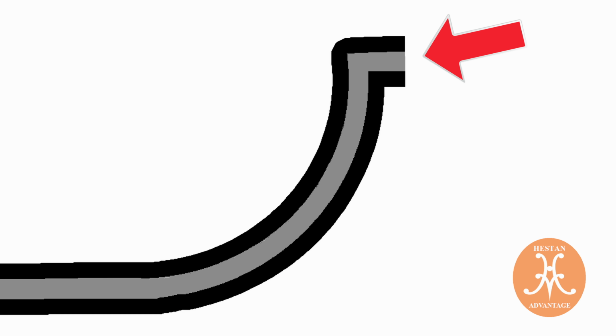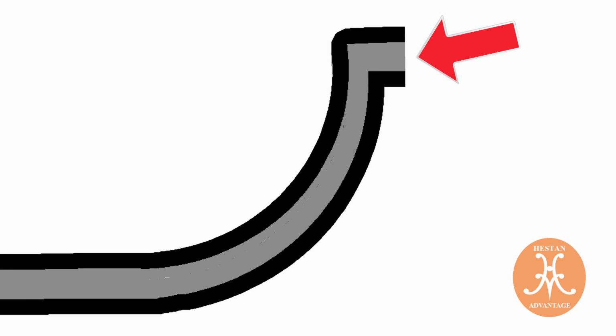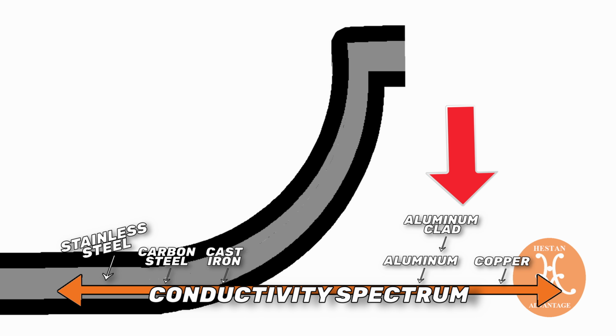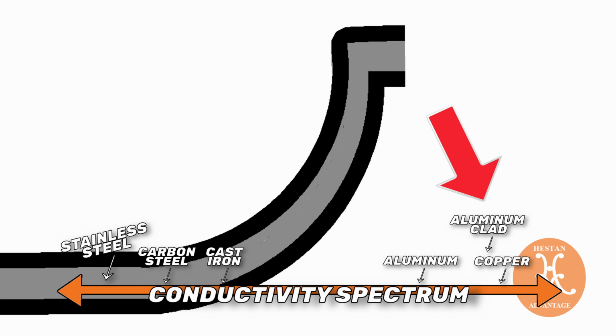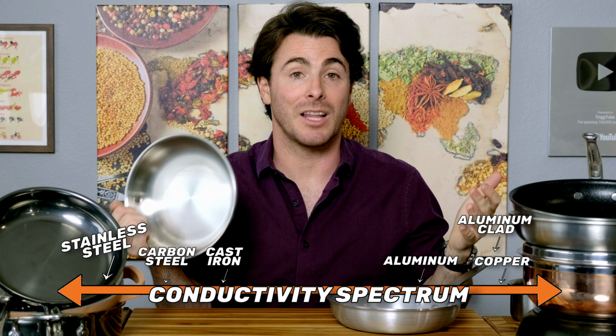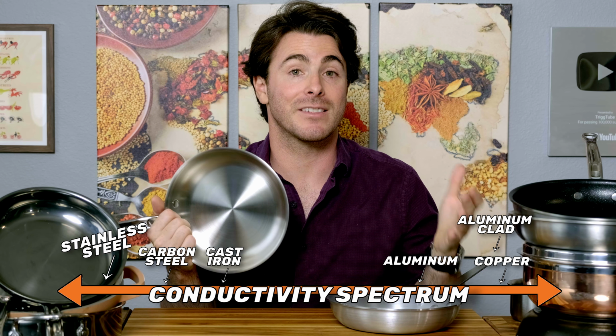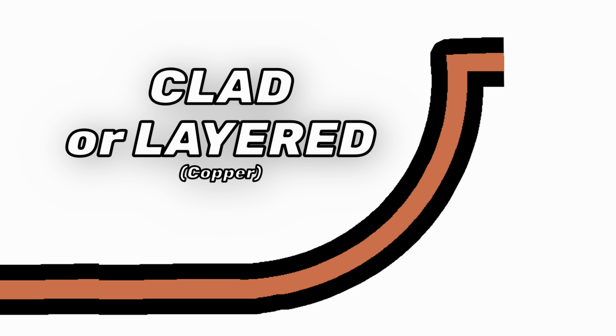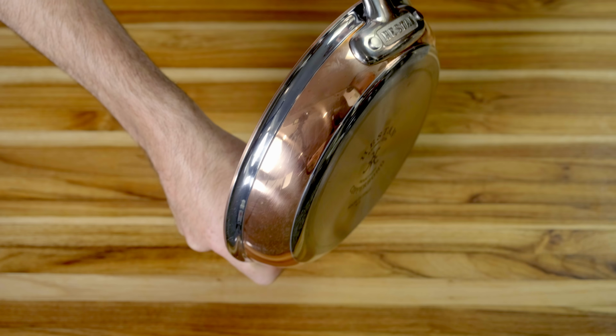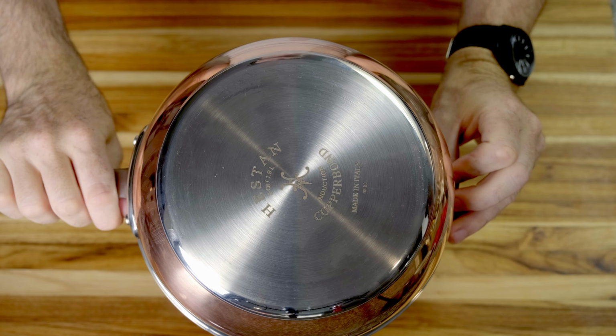And by adjusting the thickness and purity of an aluminum core, you can increase the conductivity of a clad pan up to 35%, resulting in a level of performance that's typical of a solid copper pan. But with extra durability and easy cleaning. Exactly. Having stainless steel on the top and bottom of copper cookware makes these much more durable and safer to use. Plus, having stainless steel on the bottom makes these compatible with induction stovetops that you otherwise can't use with pure copper cookware.